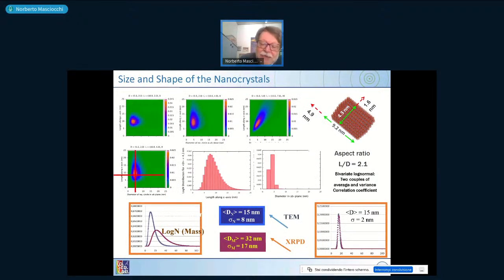Normally, when you have an ensemble of material, you don't have crystals which are all the same size and all of the same shape. The example I give you here is a system we studied in the past, which has this kind of prismatic shape. The crystal you see here is 4.3 nanometers in width and 9.2 nanometers in height, so there is an aspect ratio. This is more than twice higher in one direction. This is called 2.1, L over T. But this is one crystal.